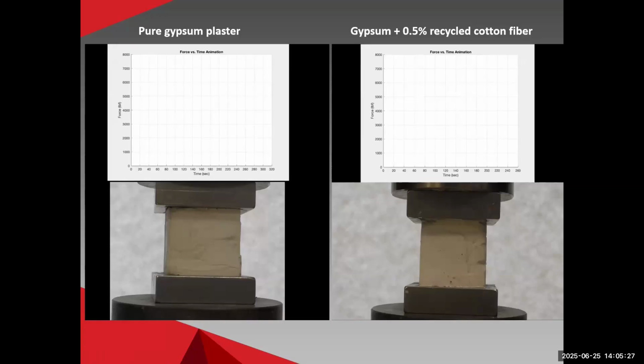So these are examples of some materials, not super resilient materials or super strong materials, but something I'm trying in the lab with is making plaster type materials out of gypsum, which is calcium sulfate, and combining very small amounts of recycled cotton fiber from clothing that's recycled using sodium hydroxide and some of the other methods I mentioned. So here's two examples, two nice videos my student made that'll show the force versus time, and you will see the increasing force, and then you will see what happens as it breaks, as we're loading more and more weight onto it, in a sense.